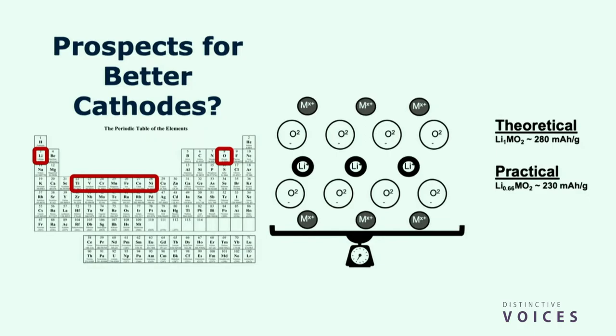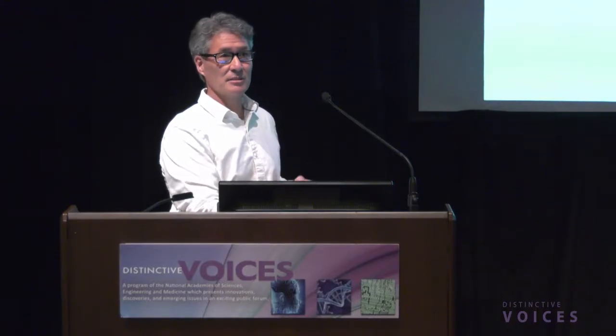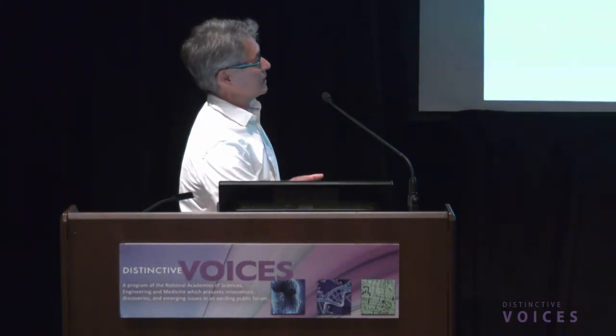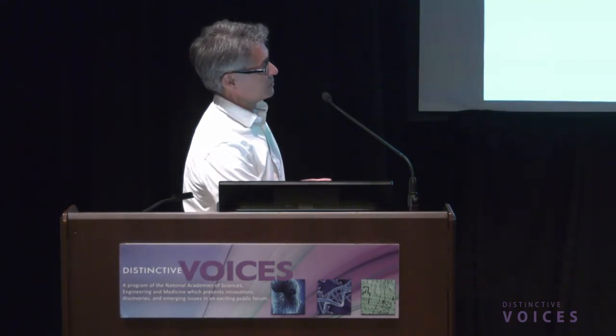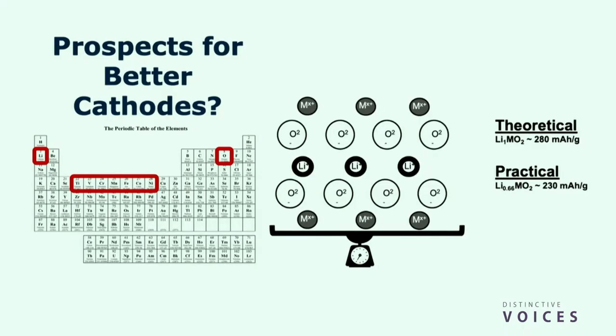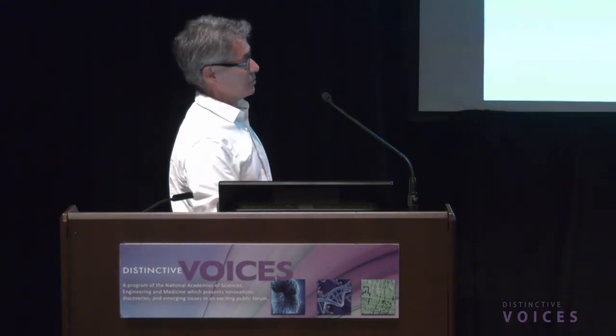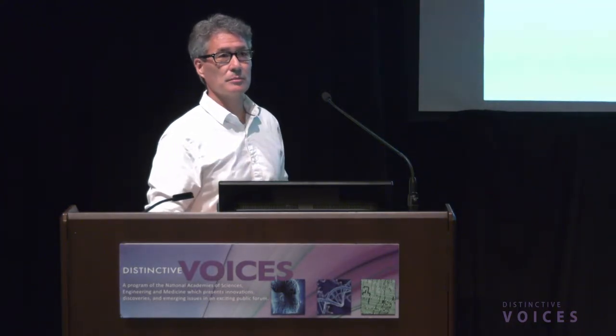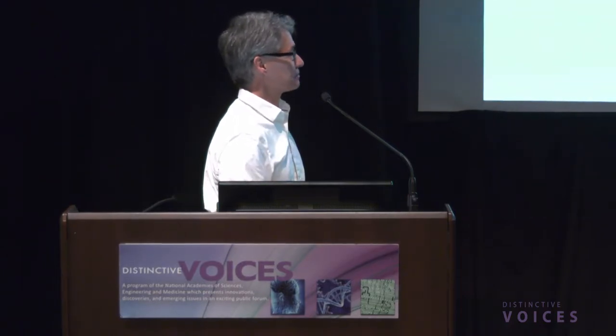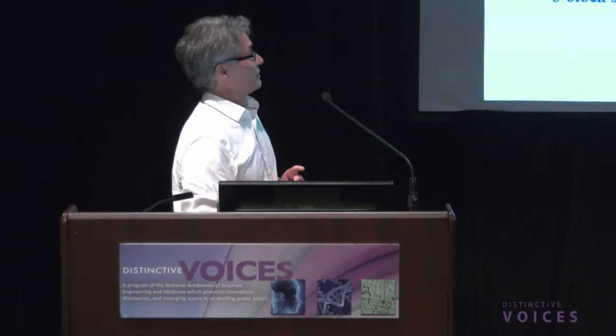But if you think about a parking garage, if you think about lithium as the pillars in a parking garage, if you take out too many pillars, that parking garage is going to fall. So you can't take out all that lithium, and so instead of reaching the theoretical value, you have to keep some lithium in there. The practical value is about 230 milliamp hours per gram. So if one asks me how much better can a cathode get, I think we're pretty much close to the maximum limit for the cathode performance. But there's one more thing.